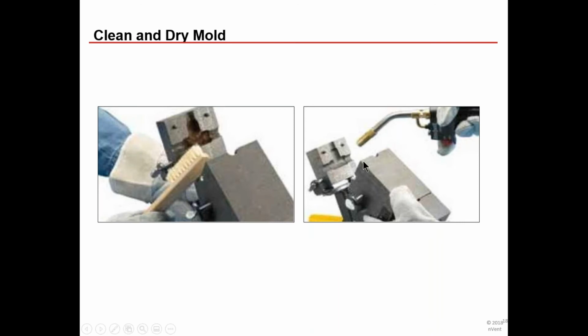So it is imperative that you heat up the mold with a blowtorch. And if there's a lot of moisture in there, you can actually physically see it evaporate out of the mold. Once you have done this and you do an initial weld, it's already hot enough that the moisture is not a problem, and you can keep using it throughout the day unless you let it sit for a while and it's really humid, things like that. Then you might want to blowtorch it again. But if you're continuously doing it throughout the day, blowtorch it in the beginning of the day before your first weld, and you're good as you continuously use it. You don't have to do that every time that you do a weld, just when you initially start for the day.